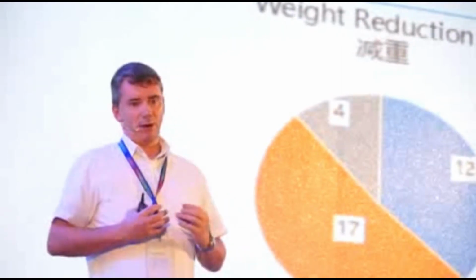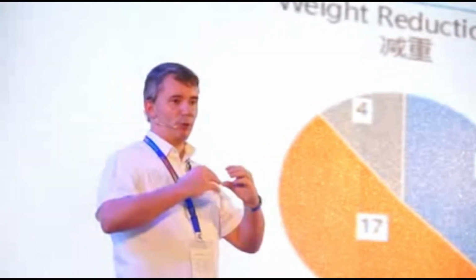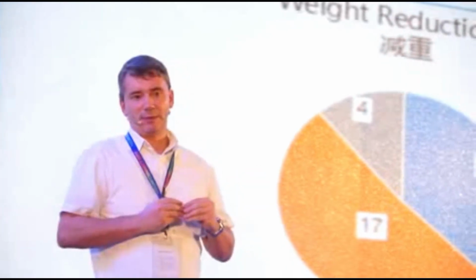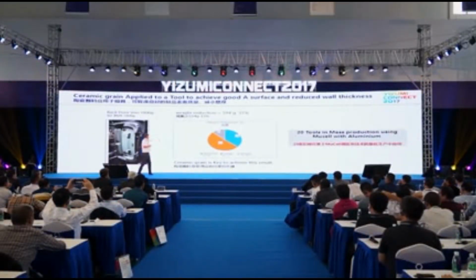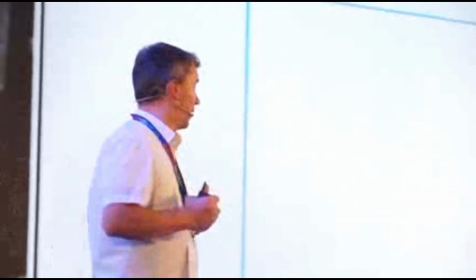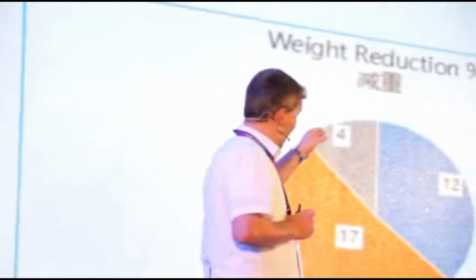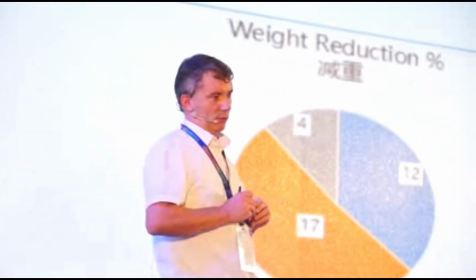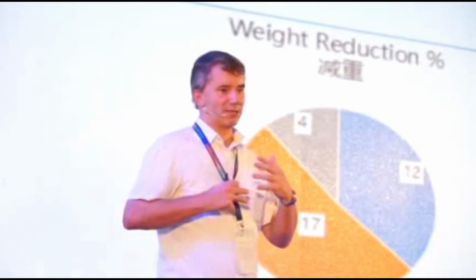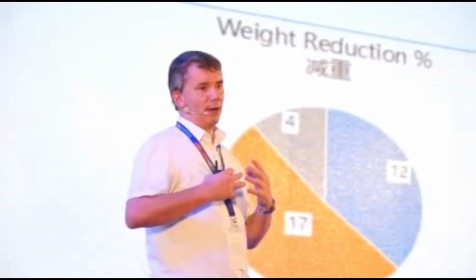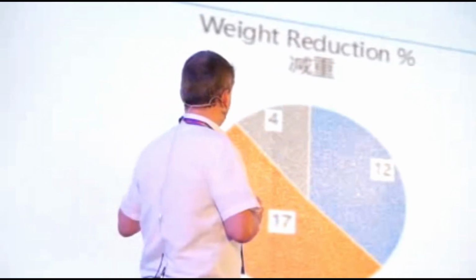Because we don't have the sink mark, the ratio between the A and the B surface doesn't need to be 30%. So we reduced the wall thickness of this product from, I think it was 3 millimeters to about 2.4, something like this. So the foaming allowed us to do that, and that was the key. We had a reduction of 12% by changing the material. So earlier when I said challenging all the standards, the company had a mineral-filled talc that they insisted was necessary for this product, but we found an unfilled polymer that could nucleate well, and it passed all testing and evaluation. So that wasn't a blocking point.